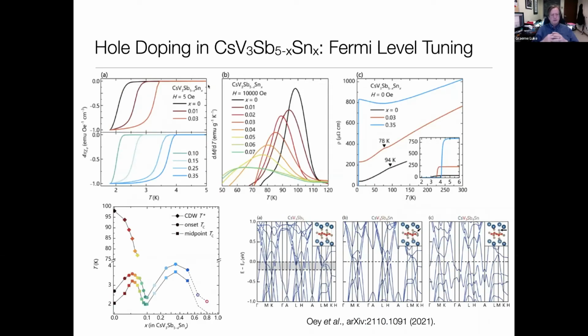The next thing we did in this experiment is to look at what happens if you move the Fermi level around. So it turns out that you can take cesium vanadium 3 antimony 5, and you can change some of the antimony into tin. And this essentially is a way of hole doping the material, and you can change its properties quite a lot. So here's showing you, for example, the magnetic susceptibility. First of all, for fairly low amounts of doping, even 3% doping actually causes the TC to rise rather dramatically from about 2 Kelvin to more like 3 Kelvin. So that's a 50% increase in TC with just 3% substitution.